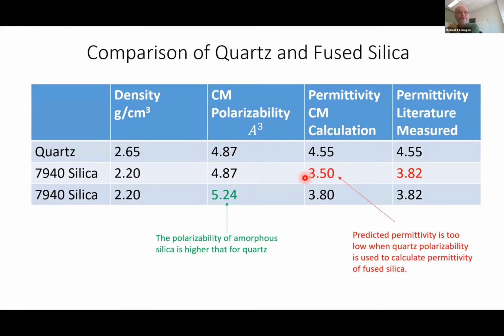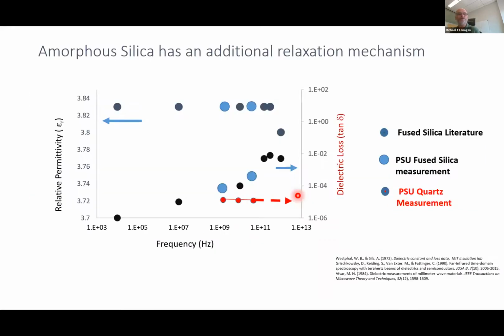So what does that mean? Basically, we have an extra polarizability or an extra polarization in glass. So we would need this polarizability value in our CM calculation to match the predicted and measured values. Okay, well, that has a profound effect on dielectric loss in the 5G frequency range. So we have this extra polarization mechanism.